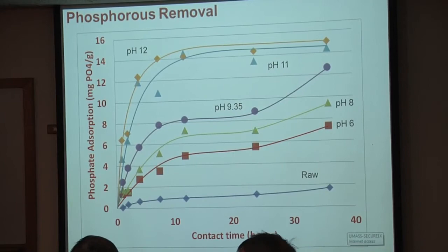Q: So those represent a saturated state? A: After about 10 hours, yes—at least a monolayer saturated state. We get some interesting multi-layer behavior after that. I'm working with small volumes of about 50 milligrams for these trials, so I'm still in a very heterogeneous material range and I'll see some fluctuations. No matter what I do, I always get this really nice first layer formation that behaves very well—it's the multi-layer behavior after that which gets a little unpredictable.